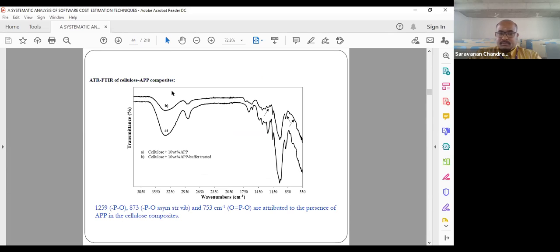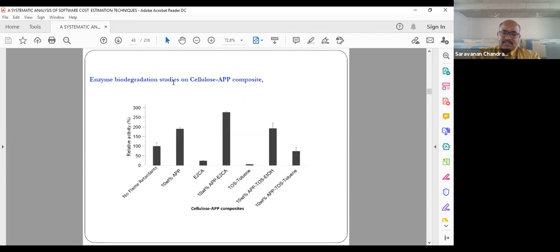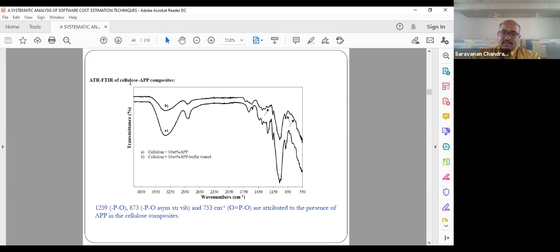Go to the slide before, ma'am, the first slide. As I showed you, APP is leaching out from the film. Next slide. We have confirmed with FTIR that the phosphate peak is reducing, which indicates that APP is a very good flame retardant, and a very good material for mechanical properties. It is also suitable for biodegradation. The surface-treated samples are also very good materials for printing as well as flame retardancy.